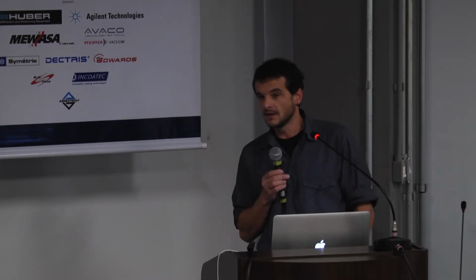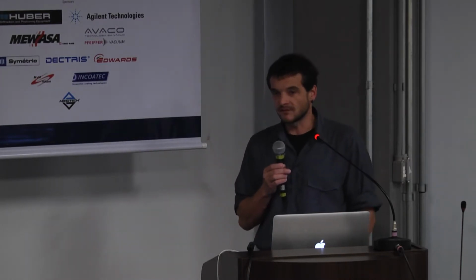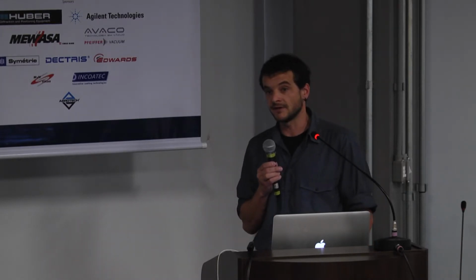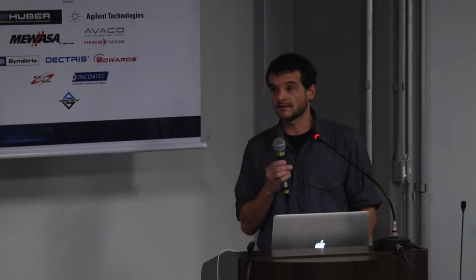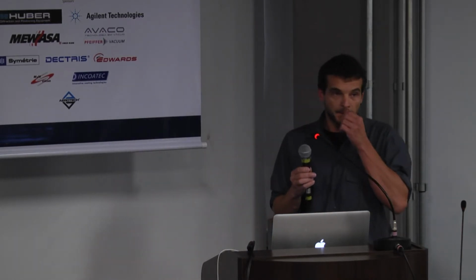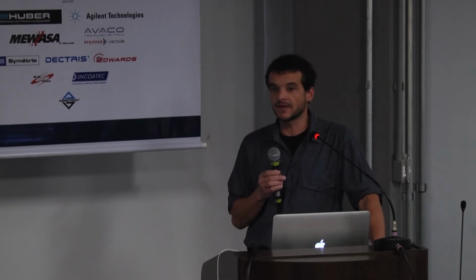The problem in tip-enhanced Raman scattering is that the signal to noise performance is rather weak. That's a problem, and so the community suffers a lot from irreproducibility, and it's difficult. Also, I have to say that there are amazing results. People achieve submolecular resolution with TERS that we have not achieved yet. They go to STM and high vacuum, and there are a lot of interesting results going on. It's amazing, fascinating.